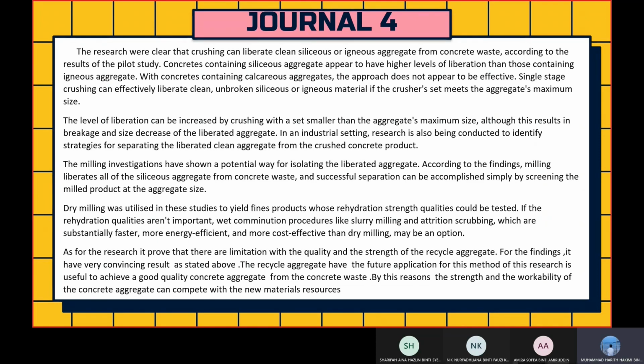The level of liberation can be increased by crushing with a set smaller than the aggregate maximum size, although this may result in the breakage and size decrease of the liberated aggregate in an industrial setting. Research is also being conducted to identify strategies for separating the liberated clean aggregate from the crushed concrete product. The milling investigation has shown a potential way of isolating the liberated aggregate.